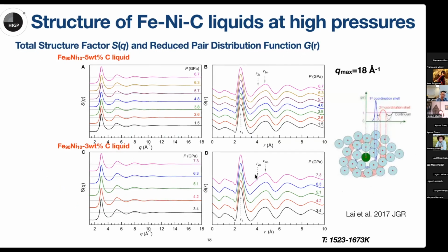After we measured the multi-angle energy dispersive X-ray diffraction pattern, we can determine the total structure factor of the liquid as a function of pressure up to 7 GPa. And by doing a Fourier transformation of the structure factor, we could get the pair distribution function of this liquid at high pressures. Basically, the pair distribution function is the probability of finding another atom around a center atom. The blue line here shows the first coordination shell, and the red one shows the second coordination shell.